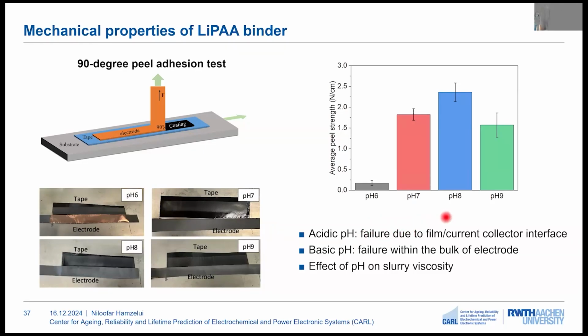At higher pHs, we have a higher average peel strength, which is again decreasing by increasing the pH to 9. And in the basic pH, we see that the electrode is still sticking to the copper foil, but some parts of the electrode are sticking to the tape after the measurement. And this indicates that there is a failure within the bulk of the electrode.